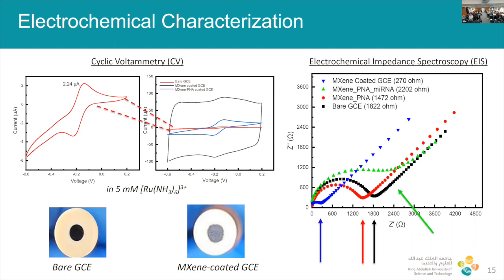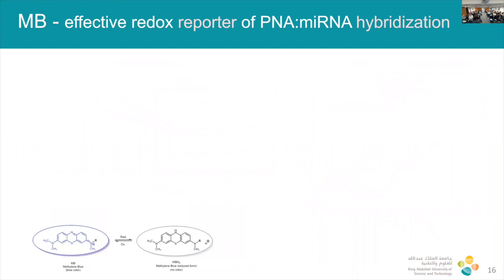We really want to make sure that what we're seeing here is a specific interaction between PNA and microRNA. And so for the next experiments, we chose a specific, let's say, redox label that is specific towards the hybridization. So if there is a duplex, then we should see this signal arising. For that, we chose to use methylene blue, the most commonly used redox label. You see this is a nice heterocycle, and the nice thing about it is that it interacts with nucleic acids in various ways. It can interact with single-stranded nucleic acid just through an electrostatic interaction. And it interacts with double strands, so duplexes, obviously with intercalation, and some groove binding can also happen. So great, we've chosen methylene blue as a reporter of this PNA-microRNA hybridization.